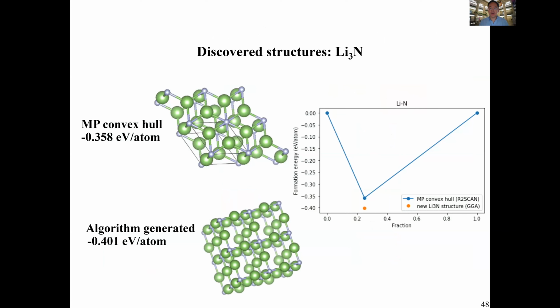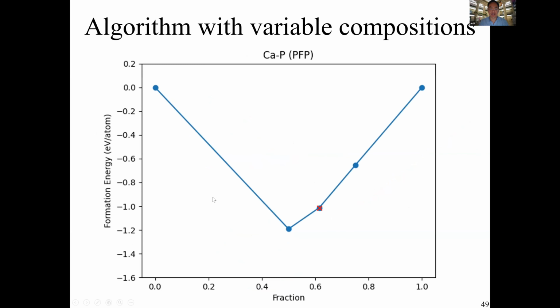So what we do is we take the structures in the ground state in the Materials Project, and then we run the PFP potential, and we also have a PFP convex hull, which is not necessarily the Materials Project hull, but after we find some new structure which breaks the PFP hull, we then calculate with GGA. We can only do GGA because our PFP is fitted to GGA, so we should not run other potentials, because our PFP is only supposed to reproduce GGA. So at least in the GGA hull, we're able to break the GGA hull in this lithium-3 nitride case.